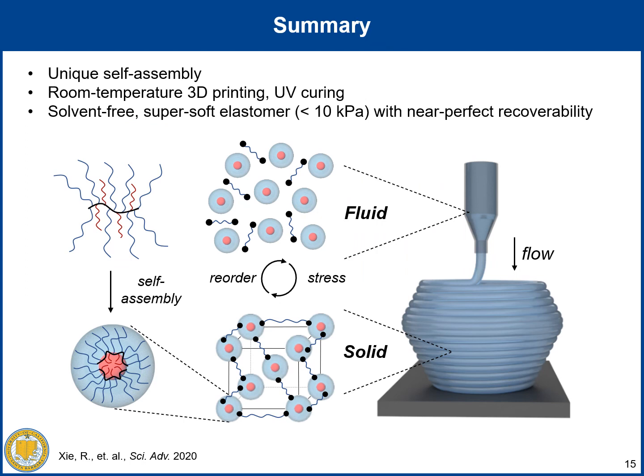In summary, hopefully I have conveyed that we have made some tremendous progress in improving the processability of bottlebrush elastomers by designing a novel photo-crosslinker and a novel bottlebrush statistical polymer. Specifically, we have leveraged the unique self-assembly of bottlebrush statistical polymer into body-centered cubic morphology to induce the yield stress fluid behavior, which in turn allows room temperature 3D printing.